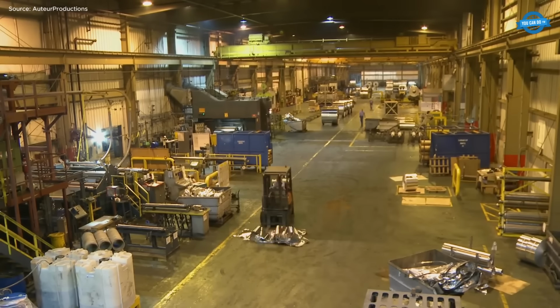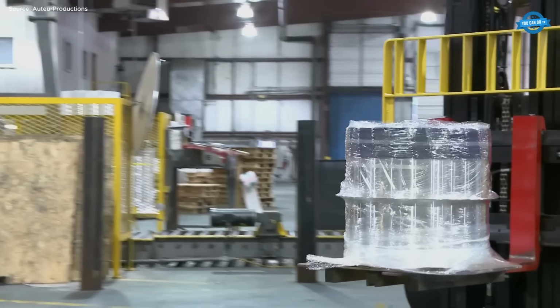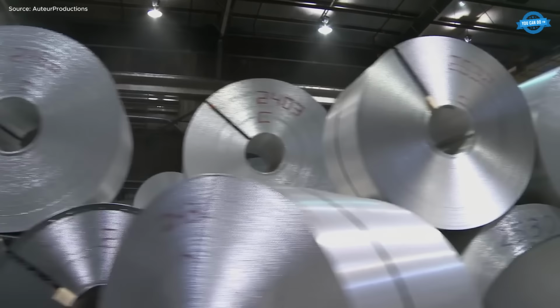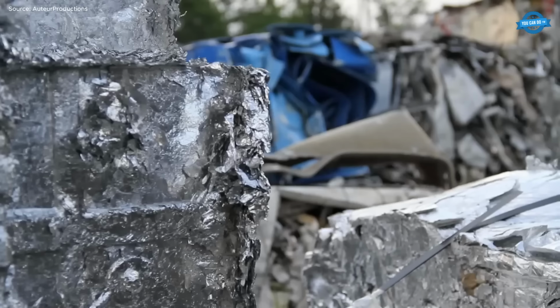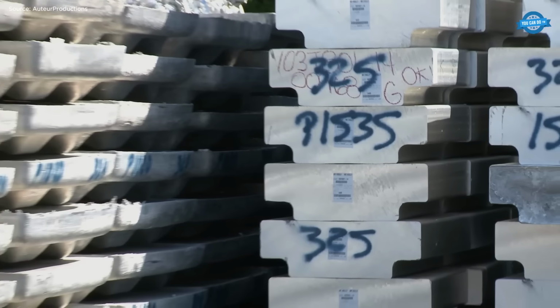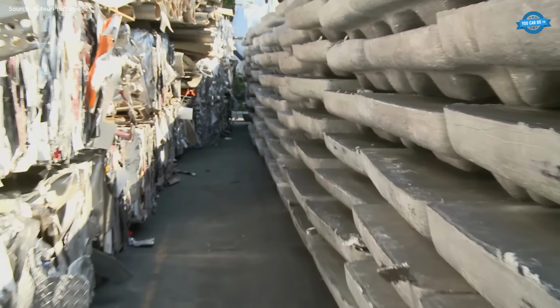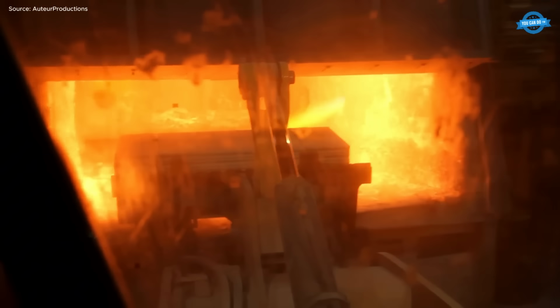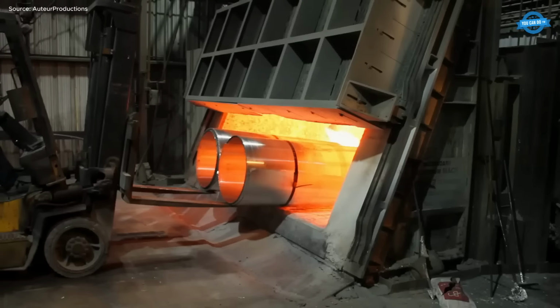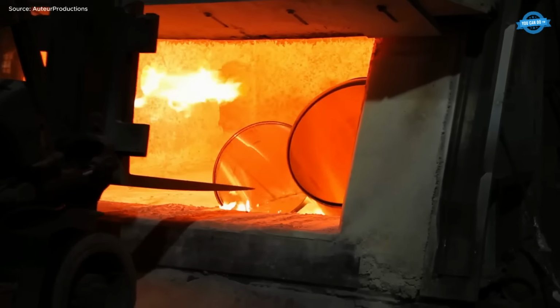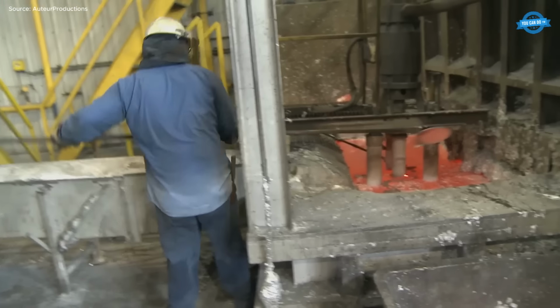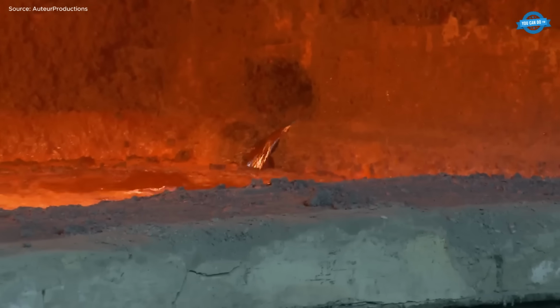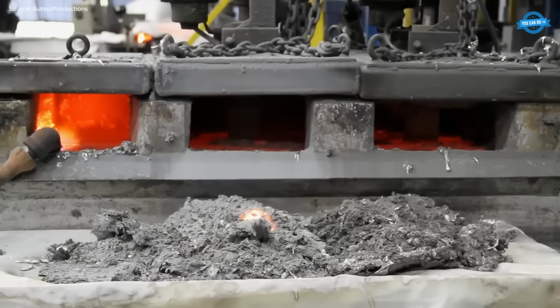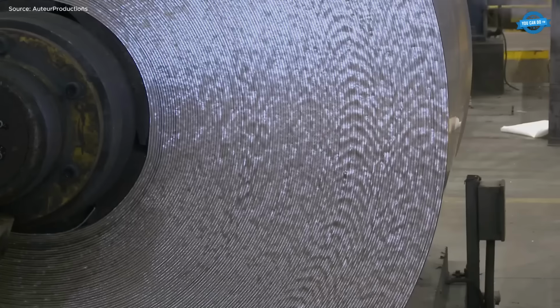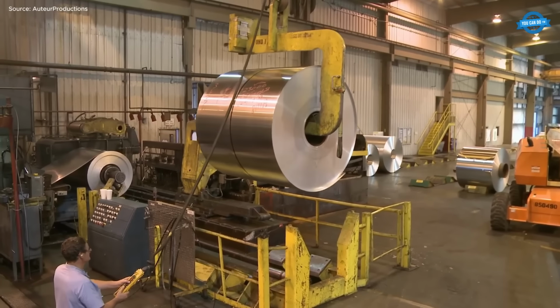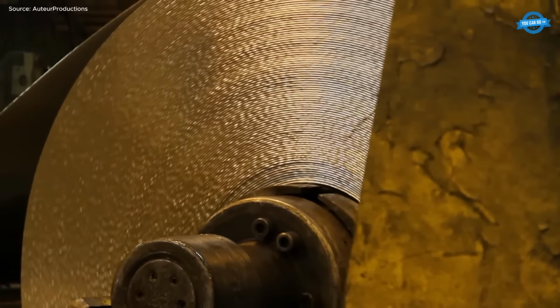JW Aluminum Rolling operates 24/7 across 4 U.S. facilities to produce rolled aluminum products used in HVAC coils, kitchenware, gutters, and packaging. The process begins with a mix of prime aluminum ingots, at least 99.7% purity, and scrap, including post-industrial and customer-returned material. This blend is melted in furnaces at over 1,000 degrees Celsius. Once molten, aluminum is transferred to a holding furnace, up to 60,000 pounds capacity, then cast into coils using a twin-roll caster. The metal solidifies between water-cooled rolls, forming a cast coil in about 6 hours.